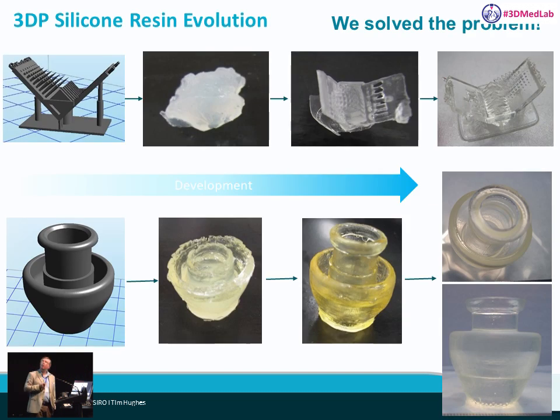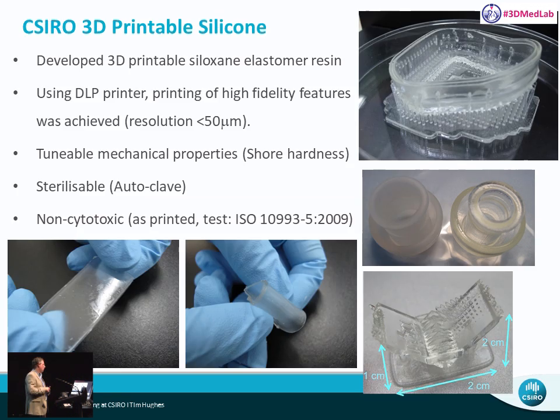So I also want to talk a little bit about our silicone work. This is actually a lot harder than the previous work. The silicones are a much softer material, and have a really low Tg. So our early attempts at making these designs were pretty poor. And that's because of plastic deformation during the 3D printing process when you lift up the part, peel off the bottom of the vat. But we persisted and we were able to improve the formulations, and you're starting to see that we can make parts that at least start to replicate what we wanted to make.